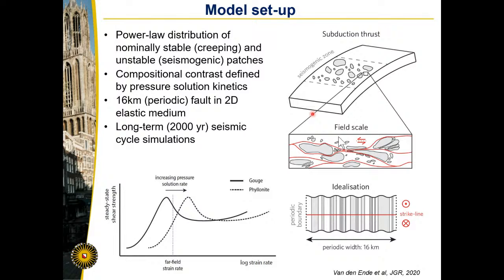So in our model, we input these asperities according to a power law distribution. So we have two different materials, a gouge material, which is frictionally unstable at our loading rate, and we have our creeping material, which is frictionally stable at the loading rate. And the only difference between these two is the kinetics of pressure solution. So the phyllonite, the stable material, has faster pressure solution kinetics than the gouge material. And that's the only difference between the two. We distribute this material along our fault, which is simulated at 300 degrees C, so at a certain depth level.